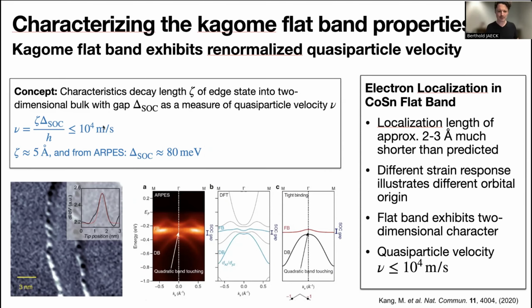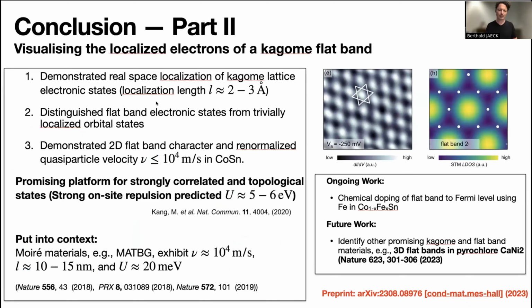So how can we put this in context? When you think about flatband electronic states, what we want are electrons that are very localized, so that the many-body Coulomb interactions between these states can take over. I've shown you now that in cobalt tin, the states are very localized and that the flatband is relatively flat, with a very small quasi-particle velocity. When we compare this to, for example, magic-angle twisted bilayer graphene, we find that the effective quasi-particle velocity in cobalt tin is actually not that far away from that value.